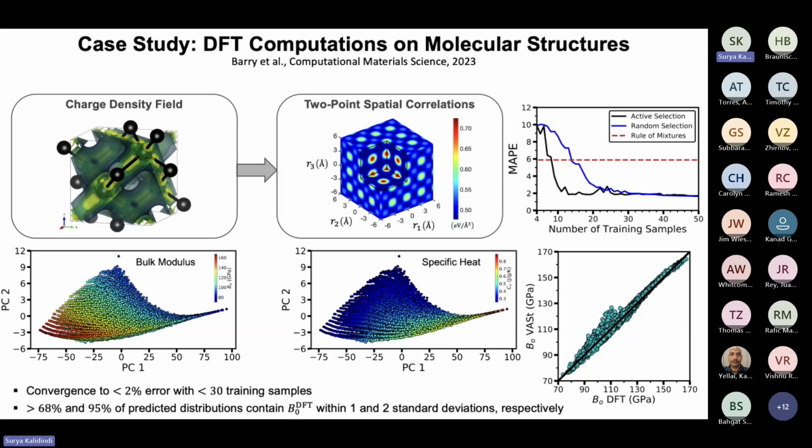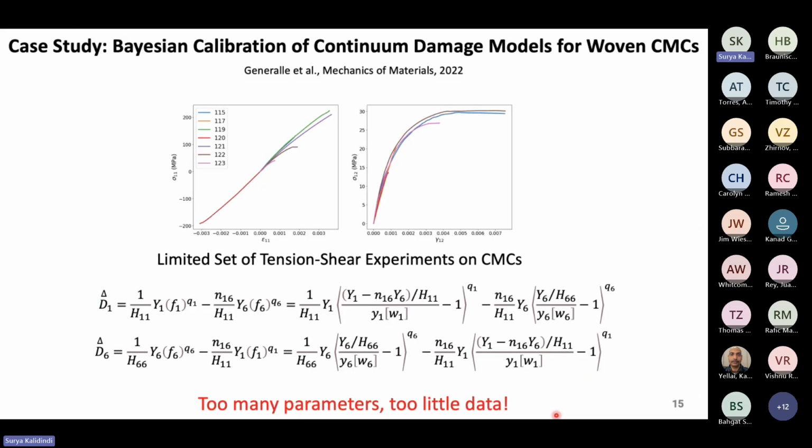And what is shown there is that because of these tools I'm showing you, we can build an effective model with as small as 10 DFT computations. That's all we need. At least for this property, that's all you need. After that, the increment in value, or what I'm learning more after 10 increments, is rather small. In other words, I might as well go try something else if I want to learn more. There's not much of a value there, right?